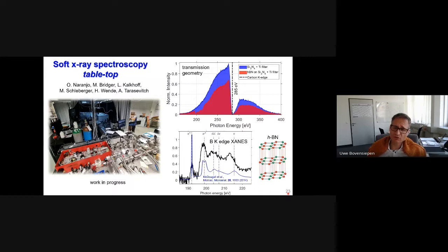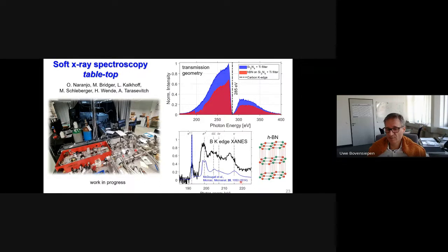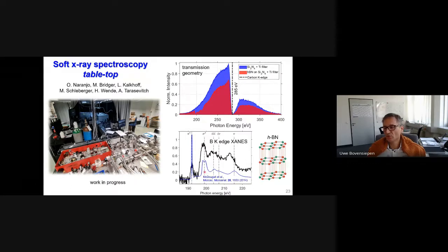Now, what we further have to do is to compare this with literature data, and I show you one spectrum from synchrotron work where they also identify these signatures, but you can see that the separation of the pi star and sigma star resonances shows quite an opposite behavior in comparison to our work, which we currently have to verify is indeed due to the well-known searchlight effect: that we here transmit in a normal direction, whereas the other work has been done under 45 degrees, where you then probe in particular very intensely the pi orbitals. All right, so this is work in progress, and I hope that in the future I can show you more on this. In particular, time-resolved studies is something that we aim at.